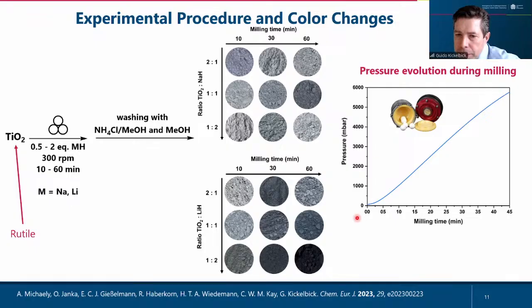Yeah. So what you can see is that over milling time, in both cases, you have a pressure increase. And this pressure increase is most likely coming from the release of hydrogen. We could test that after the experiments with a simple test. You know that you have a small test for hydrogen, and we could prove that hydrogen was in the milling jars. Okay, so we could prove something changed here.